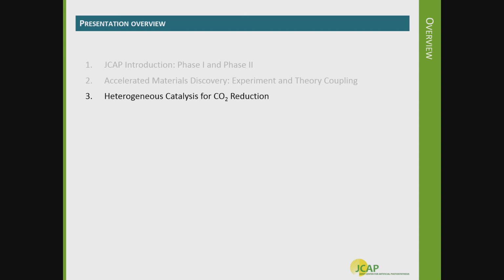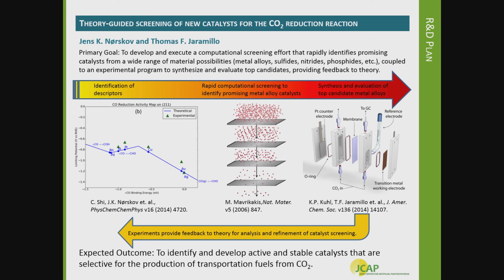So I want to spend just a little bit of time saying something about the approach that JCAP is taking in addressing the considerable challenge of heterogeneous catalysis for CO2 reduction. The approach in general across all of the efforts is to use a theory-guided approach to screen new catalysts, to identify descriptors for CO2 reduction and to compute the energy landscapes with both the thermodynamic states and kinetic barriers, and to rapidly synthesize and screen these using large area electrochemical cells that can detect the full range of products for CO2 reduction.